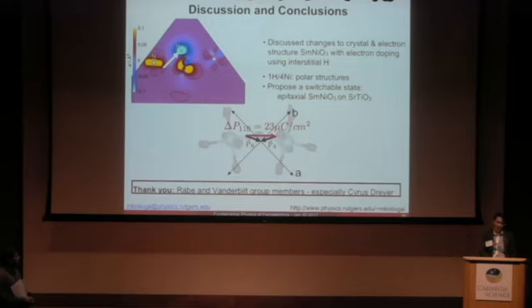I find in the calculations themselves, the nickel always wants to remain in this high spin state due to the Hund's coupling, but then otherwise it tries to minimize its overall magnetic ordering. So if you have a G-type original ordering and you add now 2 electrons, it's going to try to put the electrons on nickel so that you still have an antiferromagnetic state. If you do this with A or C, you get a similar result.